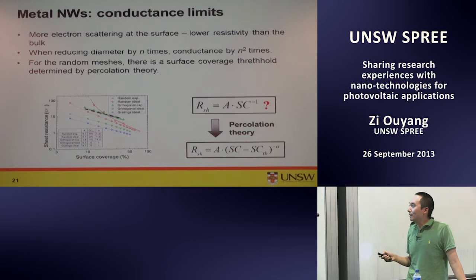Which is very interesting. We always think we have a sort of a linear relationship between sheet resistance and surface coverage. Obviously, this is log. But for the mesh nanowire, it's not like this. And we thought, oh, what's happening there? And until one day we checked, there was one standard physics model called percolation theory, which we can use to explain this shape of curve. Actually, you have a threshold, the surface coverage threshold. In this case, it's about 10%. When it's below 10%, it's just not conductive at all.